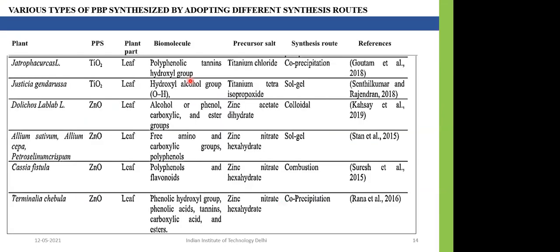So these are some of the examples of synthesized plant-based photocatalyst adopting different synthesis routes, and these are some of the varieties of plant species utilized for the synthesis of titanium dioxide and zinc oxide nanoparticles. So biomolecules such as polyphenols, flavonoids, carboxylic acids are identified to be the dominant ones. And the precursor salts, such as titanium chloride and titanium tetraisopropoxide, were mainly utilized for titanium dioxide nanophotocatalyst synthesis by following co-precipitation or sol-gel process. Whereas in case of zinc oxide nanoparticle synthesis, zinc acetate dihydrate and zinc nitrate hexahydrate were the two precursor salts utilized by following sol-gel method or combustion or co-precipitation method.